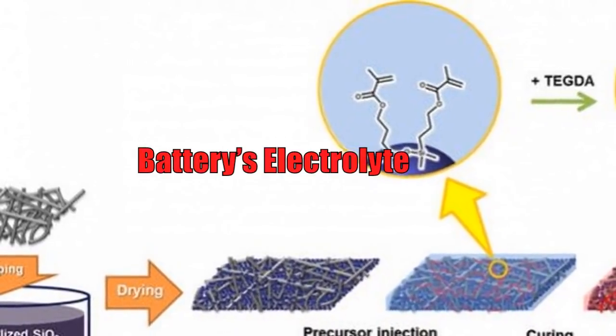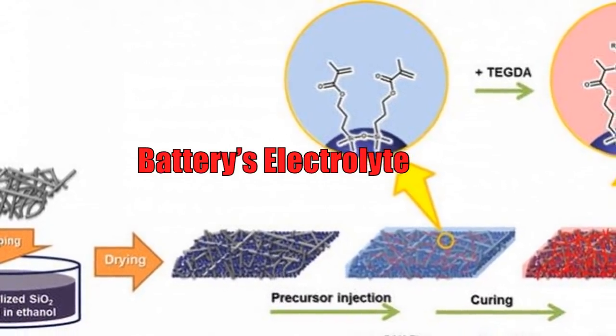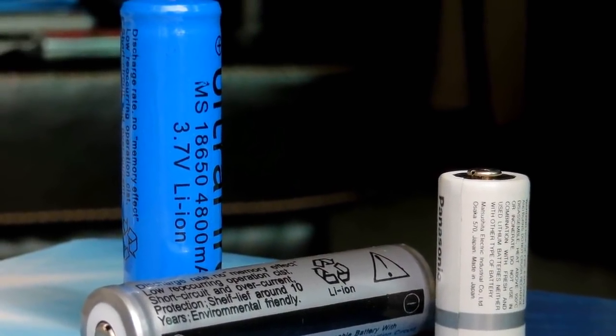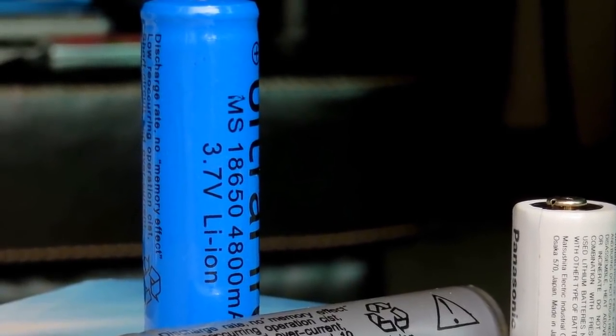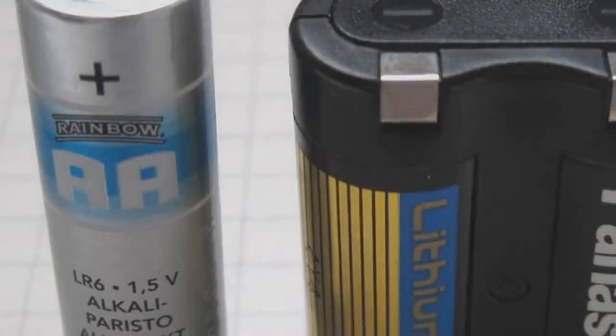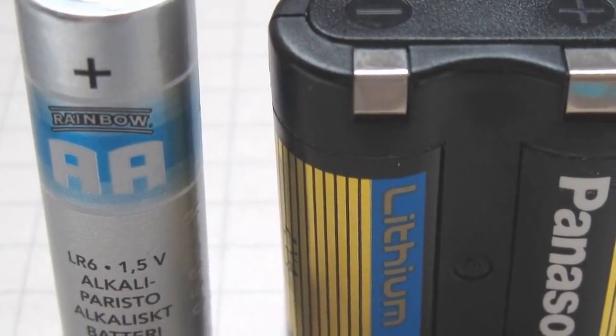An earlier project by the lab found that an anode of graphene and carbon nanotubes also prevented the formation of dendrites. Tour says the new composite is simpler. While the capacity between the former and this new battery is similar, approaching the theoretical limit of lithium metal, the new asphalt-derived carbon can take up more lithium metal per unit area and it is much simpler and cheaper to make. There is no chemical vapor deposition step, no e-beam deposition step, and no need to grow nanotubes from graphene, so manufacturing is greatly simplified.